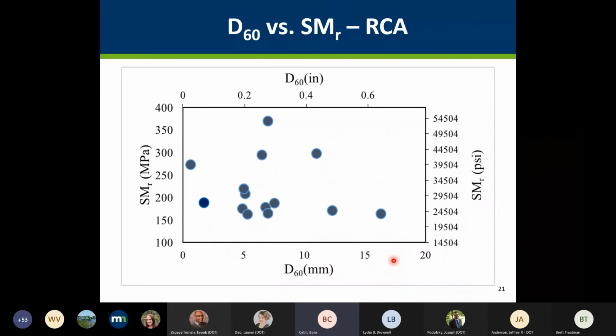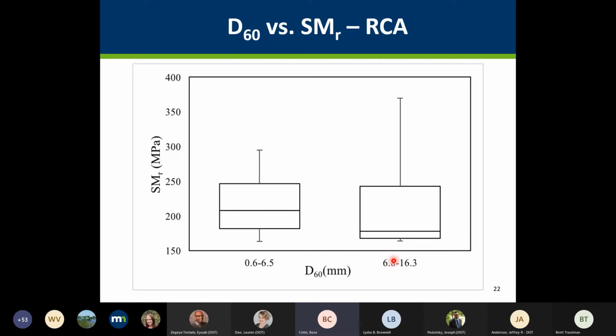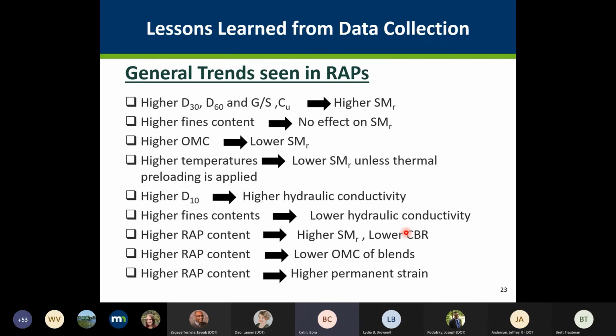And a similar comparison that we did for the recycled concrete aggregate, for D60 versus SMR values. In this case, it clearly shows that the lower the D60 value, RCA tend to have higher resilient modulus values than those with higher D60 values. And again, if the D60 value is in this range, the modulus is higher than 200, around 210, 220 megapascal, while it is 170, 180 megapascal if the D60 value is in this range for RCA materials, based on the database that we collected.